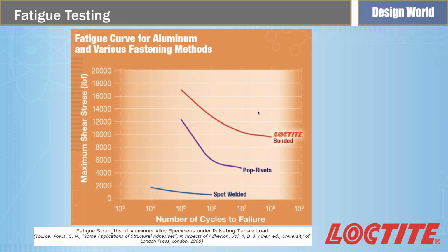This is an S-N curve where you've got your maximum shear strength along the y-axis and the number of cycles to failure along the x-axis. As you can see, the spot weld, the pop riveted, and the Loctite bonded joint. And you can see that the strongest assembly method, the one that was the most durable and lasted the longest, was the adhesively assembled joint. Actually, this is on an aluminum lapped joint, and if I put the curve for the aluminum on here, it would only be slightly higher than that bonded joint. The reason is, again, that you are distributing that stress across the entire load and not concentrating on specific points that create weak spots over time as you cycle that load. So the durability of bonded joints withstands the test of time.